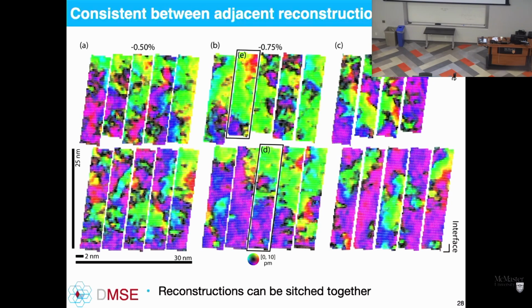And it's even consistent between adjacent regions, so I can march across my sample and reconstruct those regions that are right next to each other and then stitch them together and build up large-scale, longer-range, mesoscale information for comparison with theory. So it's not just a 1 nanometer by 1 nanometer by X nanometer thick. This is tens, if not hundreds of nanometers by hundreds of nanometers that we can acquire data from and extract out information about polarization, dopants, interstitials, defects. Single defects in a material are extractable through this technique.